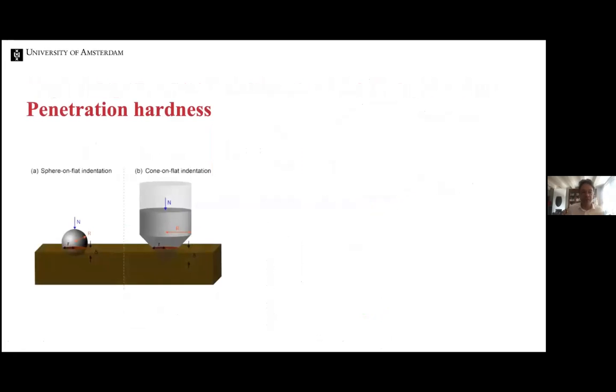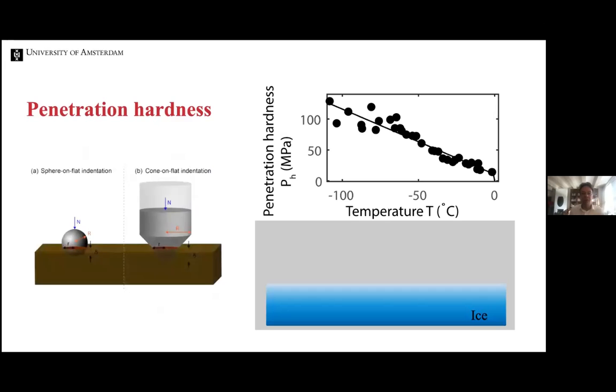Now we measure the penetration hardness of the ice. The penetration hardness measurement is a very simple measurement. You take a sphere or you take a cone, then you try and push it into the ice. You measure the force and the penetration depth, and from the two, you can directly get the penetration hardness. And so, as you might have guessed, the penetration hardness is very high at very low temperatures, but steadily decreases when you go towards the melting point.